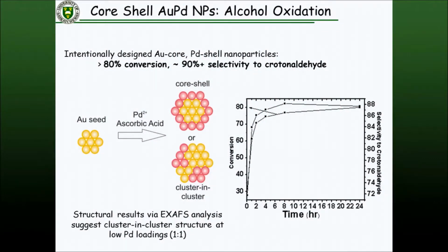But suddenly, if we mix gold particles and palladium salts together, we start to get a very active catalyst. The idea is that you make palladium 0 in the first step of a palladium salt reacting with our allylic alcohol. If you have gold particles around, there's a nucleation center available for that palladium to nucleate onto. So essentially we're making core-shell particles, if you will, of palladium reducing onto the gold. We wanted to test that. If that's the case, then if I start by making a core-shell catalyst through my sequential method, I should get a better catalyst.